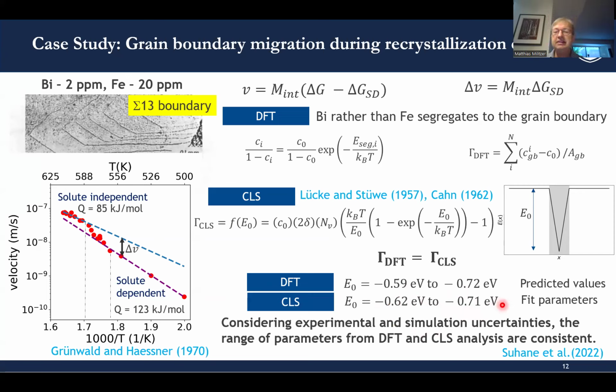And I should say that this variability that we see is primarily related to what driving pressure we have assumed for recrystallization. There's obviously a little bit of uncertainty. We have an order of magnitude approximation for this driving pressure, but not an exact number. In considering all these uncertainties from experiments and simulations, the range of parameters from both analyses are consistent. And again, this is a very encouraging result.